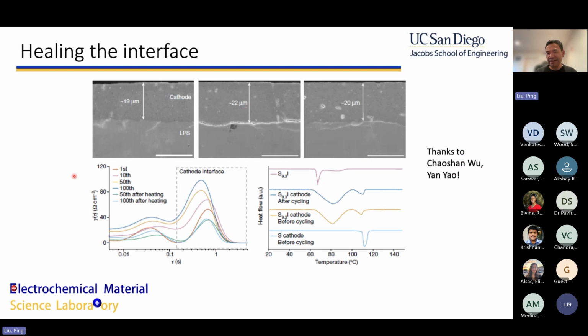And we have more direct evidence here. You will see when we first make the battery, the electrode is 19 micron thick. And after many cycles, the electrode has increased in thickness to 22. And you will also see there is a gap between the cathode and the electrolyte. That's not good. That gives you, in a local hotspot, increased impedance. However, if we reheat it, you will see the thickness partially recovers and the interface is healed.